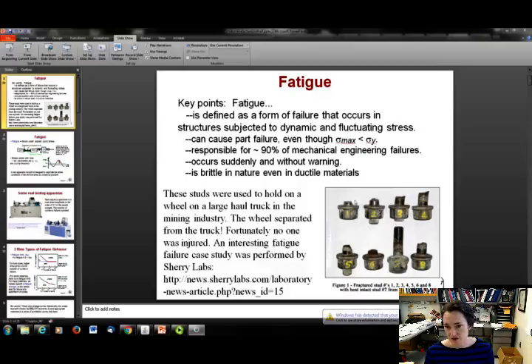You can see here, if you look at the bolts and remember what it looked like when we did those tensile tests, these do look a lot like brittle fracture. So you see these abrupt parts where you have little to no necking, and when we zoom in and look at the parts later, we'll see what the fracture surface actually looks like, but a lot of it will look like a brittle surface.